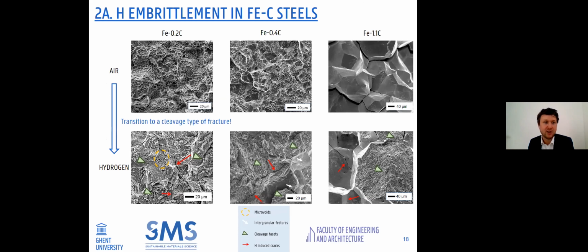So what do we see here? Indeed, that we have a transition to a cleavage type of fracture when hydrogen is added. Next to that, we also have additional hydrogen-induced cracks, as shown by the red arrows. What is the reason for this? Well, the martensitic blocks and packets are embrittled by hydrogen. This is the reason why we observe fracture as cleavage and not as intergranular failure because of trapping at the high angle grain boundaries.